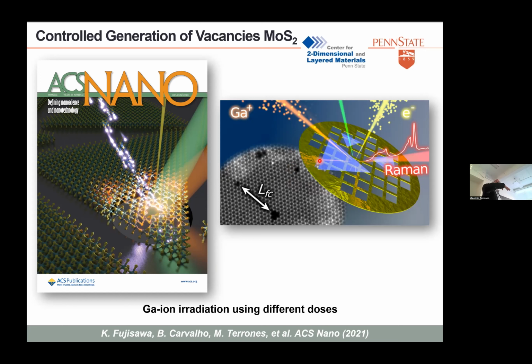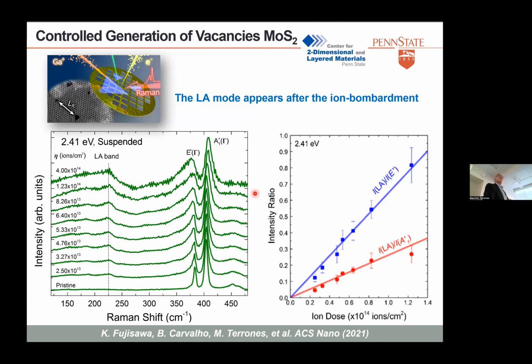We deposited the crystals, and in the same crystal we could do Raman before and after the irradiation of gallium in the same triangle, right? So we did many measurements and observations. Because what we wanted to measure is the finite crystal length between the defects, not the defect to defect distance. One thing you notice when you start putting in these ions: this is the pristine, you have the in-plane mode and the out-of-plane mode. And you start to see that the LA band starts increasing when you introduce more defects.